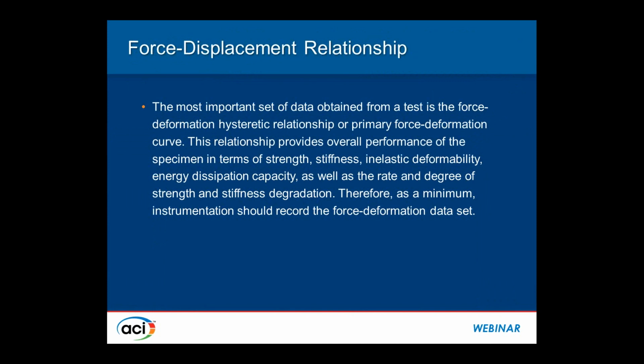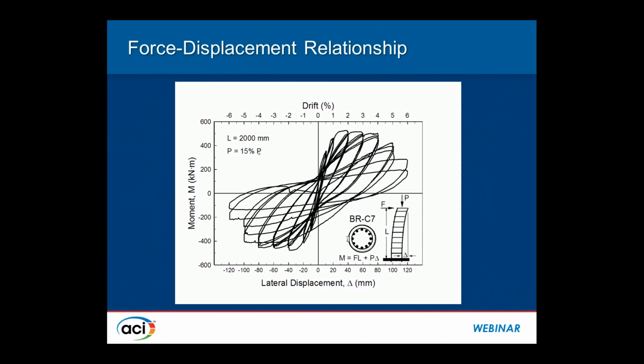And at the end, the force displacement relationship provides the single most important outcome of a test under reverse cyclic loading. This relationship, often provided as a hysteretic relationship, consists of hysteresis loops. The characteristic of this loop will tell a lot about strength, stiffness, and deformability of this member. In fact, the shape of the hysteresis loop will also shed a lot of light in terms of damage, in terms of performance of that member. So it's very important to keep good track of this hysteretic relationship and record it as accurately as possible.